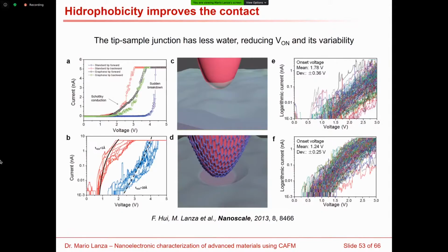So we performed some simulations and we concluded that this difference between the forward and the backward IV curve is related to the presence of a water meniscus of 1 nanometer between the tip and the sample. And when there is an electrical field applied, this water meniscus can be broken, and then the backward IV curve somehow overlaps with the Schottky conduction that is expected.